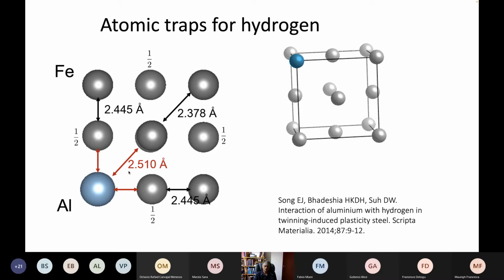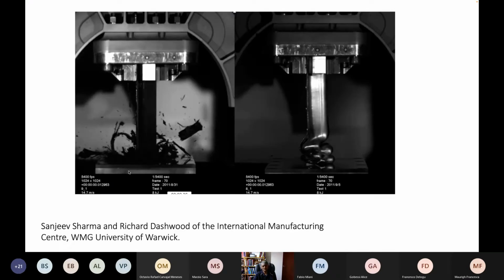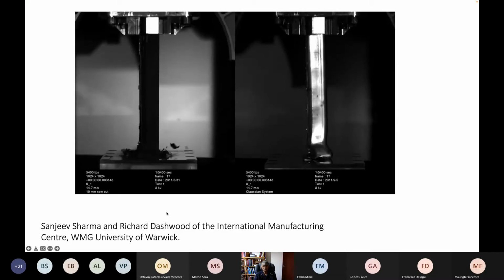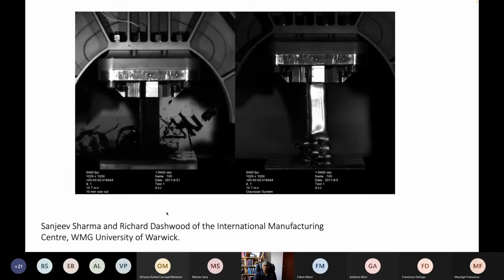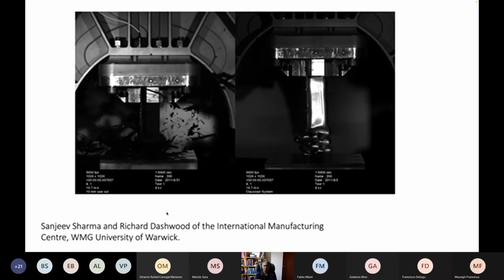automotive applications have essentially been abandoned for TRIP steels. People tried to create crash resistance using TRIP steels because they can continue to deform to a large degree of deformation. So the kind of objects I'm talking about, on this side we have a composite material, on this side we have a steel. And what you do is you want the material to absorb energy. In the case of the composite, it's by breaking interfaces between the composite components. And in the case of steel, by forming this necked structure, which basically absorbs energy by deformation.